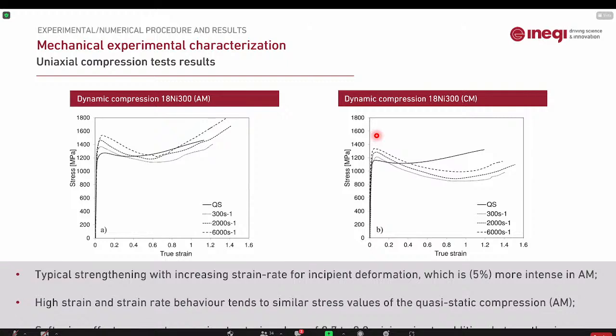With regards to the very high strain rate tests, for small strains, we note that there is an increase in the mechanical strength of the materials in both additively manufactured and conventional steels. However, for increasing strain, we notice that there is softening, and this softening can be very intense, especially in compression, in the conventional material. It goes well below the quasi-static response that we can see here.